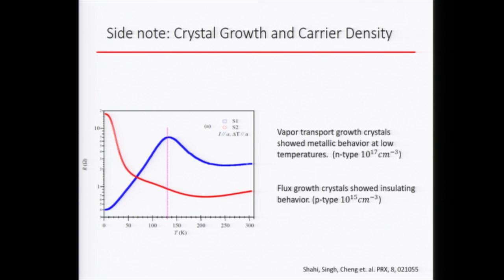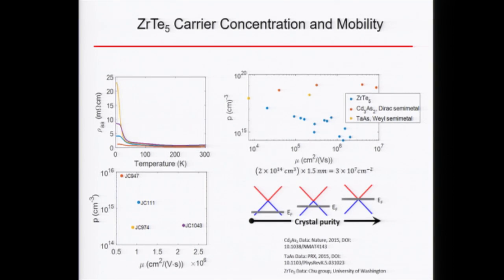But if you grow the crystal by the flux method, then you never see the peak, or you can say that peak is around 0 temperature, and the material is always P-type. The carrier density is much reduced to 10^15. My student did a bunch of crystal growth and managed to reduce the carrier density to an extremely low level. So this is carrier density from 10^15 to 10^20, and this is mobility. We tried different ways, arc melting the zirconium, and different crucibles, and eventually reached a region where you have very high mobility, about a million centimeter squared per volt per second, with a very low carrier density, below 10^15. So you're really pushing your Fermi energy close to the Dirac point.